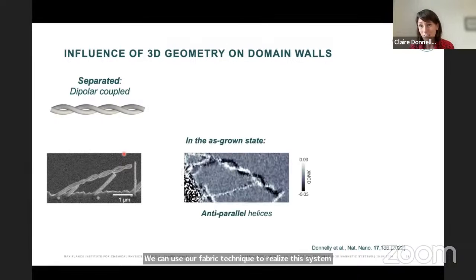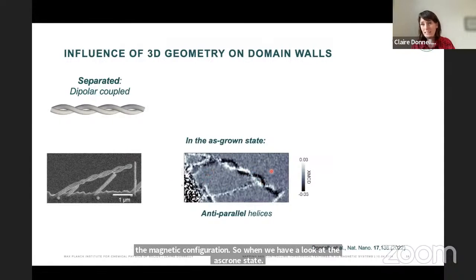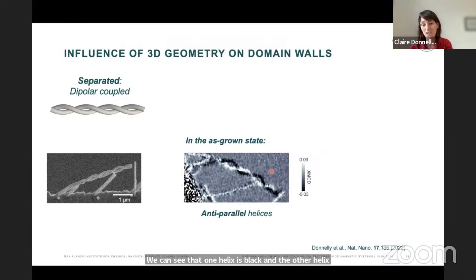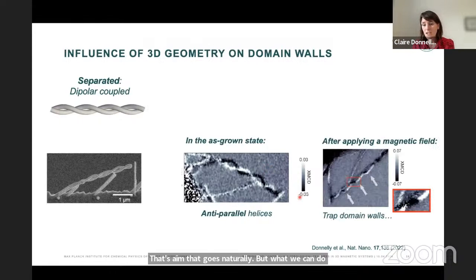And we, of course, go to the synchrotron in order to image the magnetic configuration. When we have a look at the as-grown state, we can see that one helix is black and the other helix is white, which essentially means that they're pointing in opposite directions. So we have the anti-parallel state, which turns out to be the ground state of the system that grows naturally. But if we apply a strong field perpendicular to the long axis, we can trap regular arrays of domain walls in our systems due to the geometry. And now we have this regular array of domain walls.